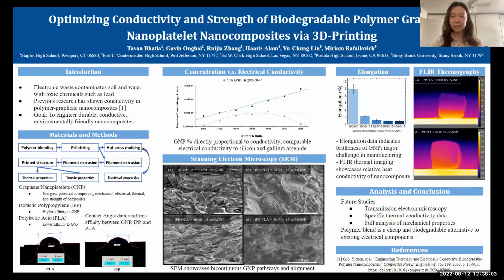Graphene is a conductive and strong allotrope of carbon, which we blended with isotactic polypropylene (iPP) and polylactic acid (PLA) at various concentrations. We hypothesized that the differential attractions for these polymers will lead to bicontinuous pathways for graphene, enhancing conductivity in a biodegradable manner.